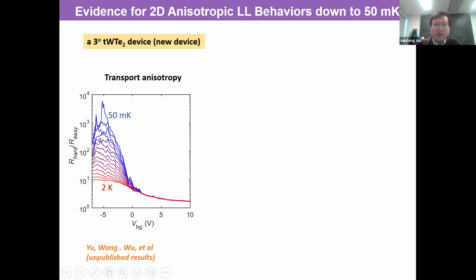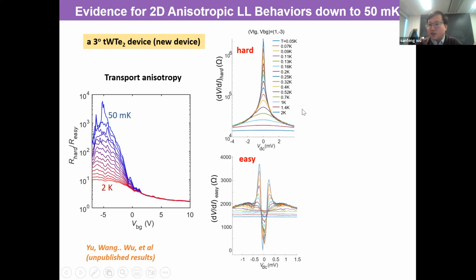And if you look at this device, again, along the hard and the easy direction, you can easily identify them. So hard and easy differential resistance as a function of bias, the same kind of measurements, but along different directions, you can clearly see the difference, right? In this case, the hard direction looks like an insulator, while the easy direction looks like metallic or even superconducting, right? So the differential resistance dV/dI as a function of bias has a peak, but it's not superconducting. Here it's a Luttinger liquid. So as long as you see a curve like this, you must think, oh, there's something very interesting. You increase the bias, you will suppress the states. So this is saying that you use a bias to kill the Luttinger liquid physics. It only happens at low bias.